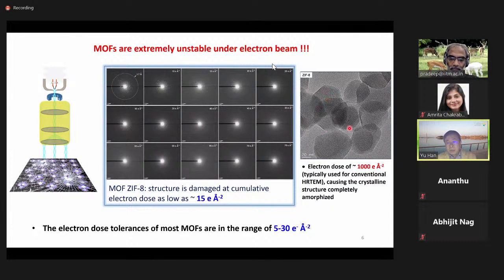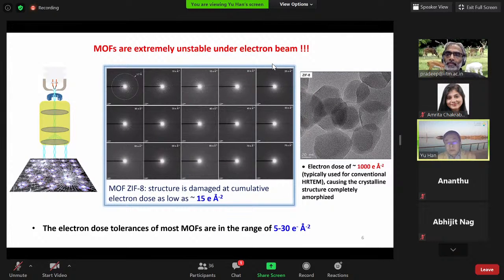However, as you can see from the image, the ZIF-8 crystal structure has been completely damaged or destroyed under this condition. We just see amorphous particles, right, without any useful information. We know ZIF-8 is highly crystalline, but we don't see the crystal structure. We only see amorphous particles because the structure has been damaged. So this result explains why conventional HRTEM is not suitable for imaging MOFs or other beam-sensitive materials.